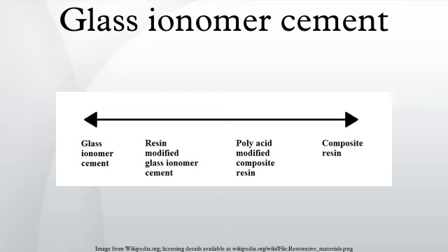Metal-reinforced glass ionomer cements, or cermets. Metal-reinforced glass ionomer cements were first introduced in 1977. The addition of silver amalgam alloy powder to conventional materials increased the physical strength of the cement and provided radiodensity. Subsequently, silver particles were sintered onto the glass, and a number of products then appeared where the amalgam alloy content had been fixed at a level claimed to produce optimum mechanical properties for a glass cermet cement.